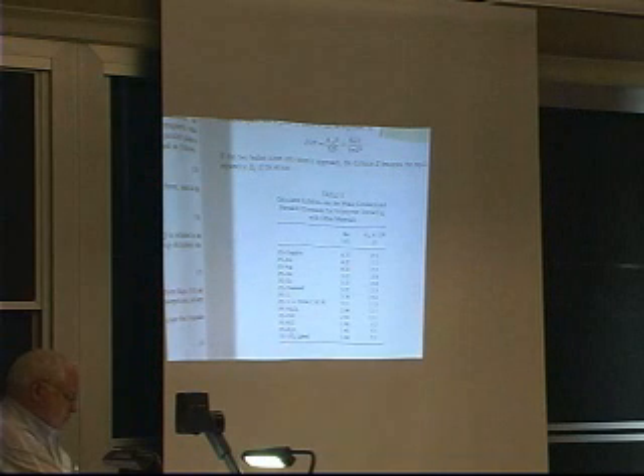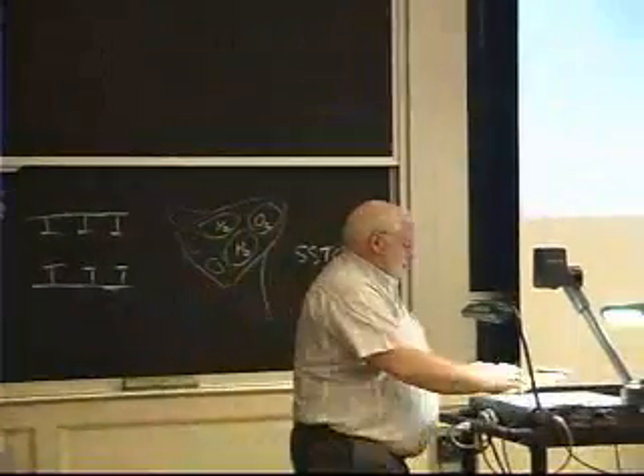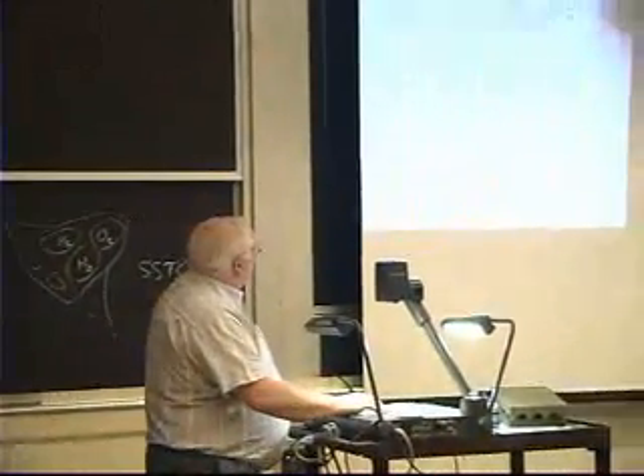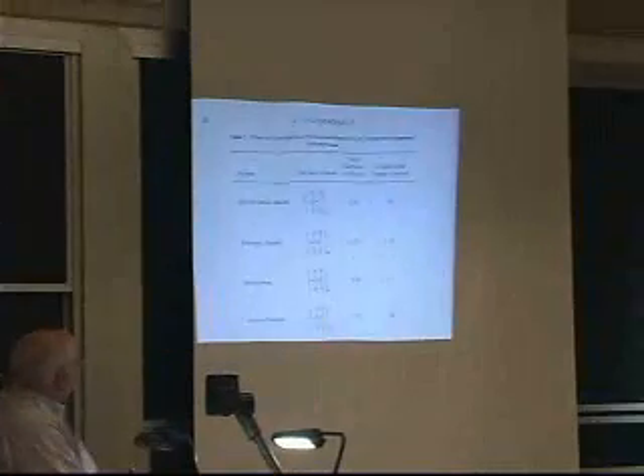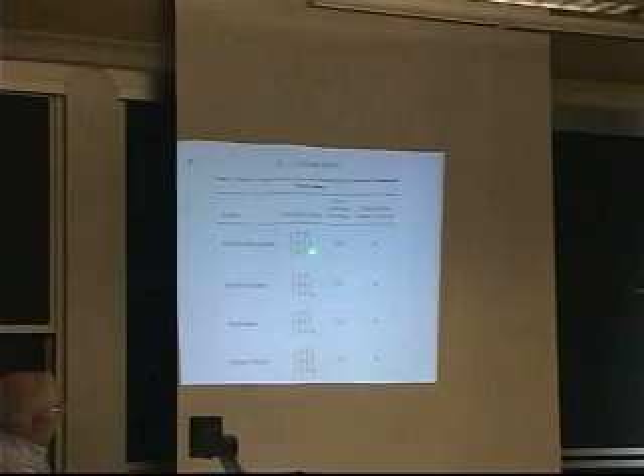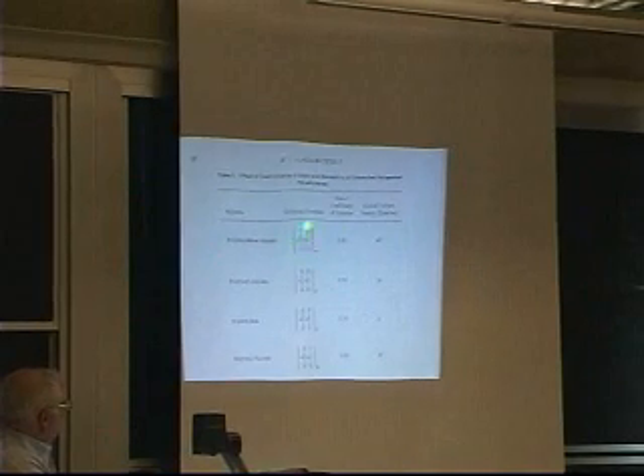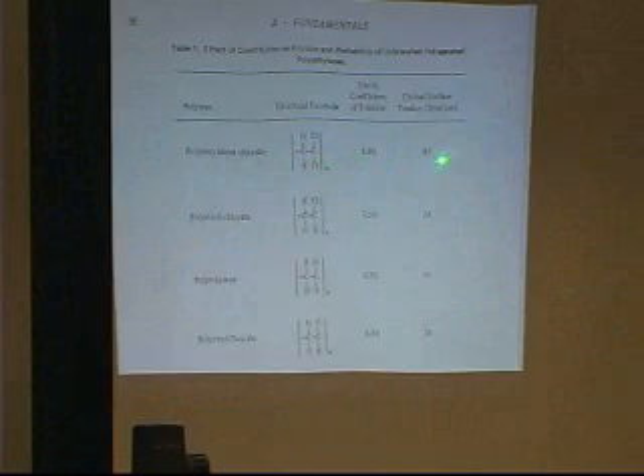The surface tension of these metals is like 1.5 joules per meter squared. The surface tension of water is 0.072. Okay, it's much, much less. The lowest surface energy materials, this comes out of Zisman, if I remember, maybe it comes out of one of these things. But if I look at my covalently bonded things, this is polyvinylidene chloride, which is 2 chlorines and two hydrogens. If this was polyethylene, it'd just be all hydrogens on a carbon backbone. And this has a critical surface tension half of water.